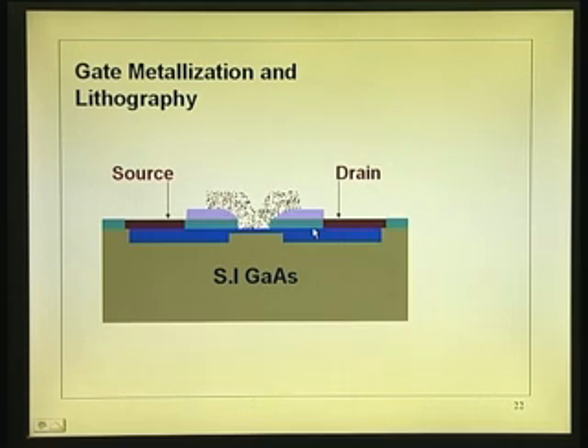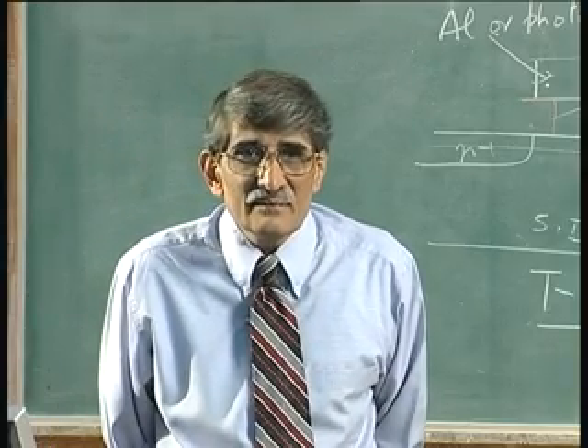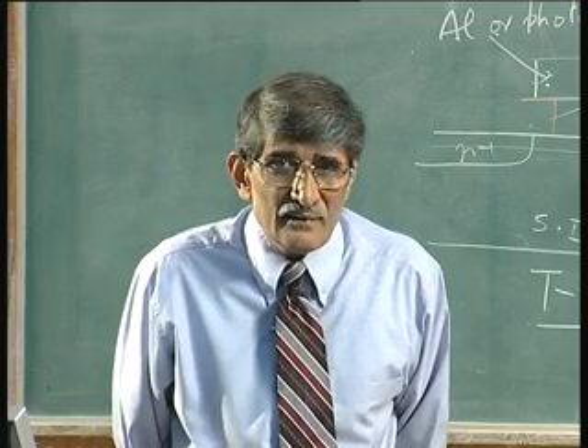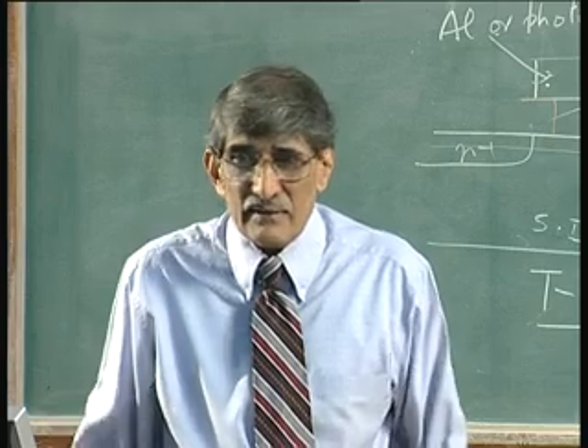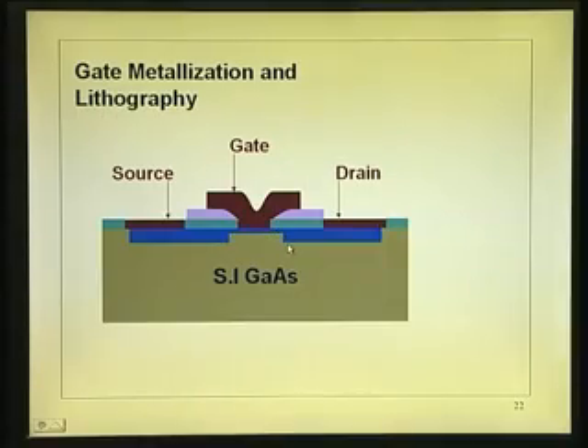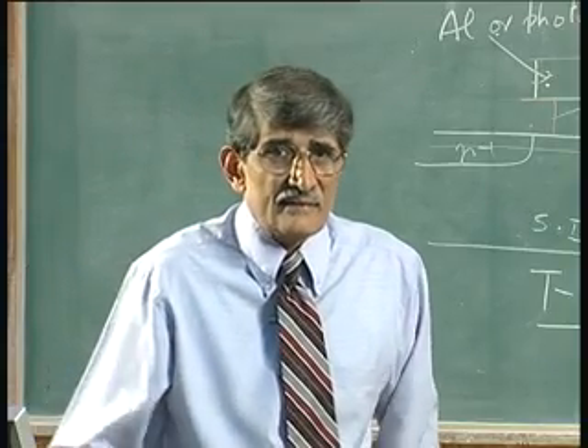In the sense, put photoresist everywhere, only in this portion. So, if I keep photoresist everywhere except this portion, I put it in acetone, the photoresist from everywhere with the metal lifted off, you will be left with this. So, the key thing here is after this step realize metal in that portion. Now, you can see you got the MESFET which is self aligned with the distance between this gate and this portion realized by that T that you have got. Okay. So, this is self aligned structure what you can get. This is a very popular technique, SAINT. Some slight modifications have come. The entire effort has been to achieve a gap between the gate and this N plus layer, controlled gate gap, which can be done with this self aligned implantation technique. Okay. So, I think the characteristics of this we will discuss next time.